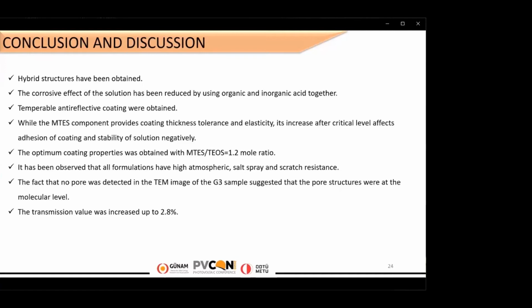The fact that no pore was detected in the TEM image of the G3 sample suggests that the pore structures were at the molecular level. Last but not least, a transmission increase of up to 2.8% has been achieved through anti-reflective coating without using any pore agents.